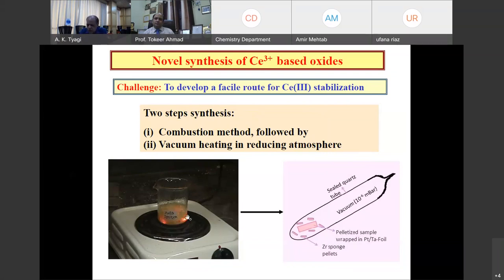Whatever product we get from combustion, make a pellet, transfer it in a platinum or tantalum foil, put in a quartz tube, surround with zirconium sponge, coupled with a dynamic vacuum, you can use a diffusion pump, evacuate and seal with an oxygen hydrogen torch or oxygen LPG torch. This ampoule has got a vacuum now, but when this ampoule goes to the furnace, this zirconium, we know from basic solid state chemistry, acts as an oxygen getter. Zirconium sponge is able to suck whatever little oxygen is present in this ampoule. So partial pressure of oxygen drops considerably in this ampoule, and because of that, you get compounds of Ce in trivalent state against what phase diagrams and thermodynamics would have predicted.